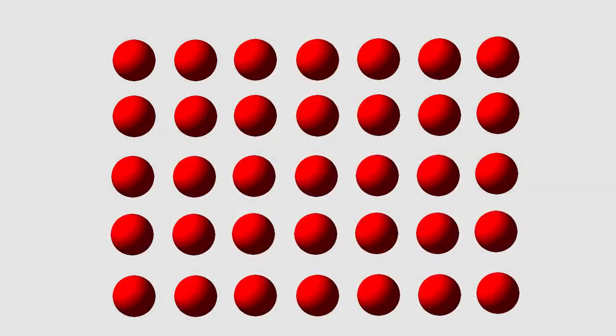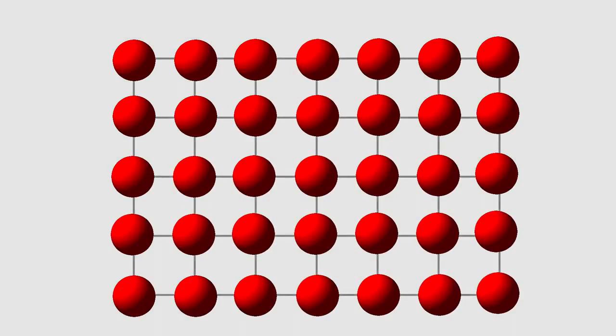Here's a simplified two-dimensional version of the atomic structure of nitinol, but one that captures the essence of why it has a temperature-dependent memory. The crystallites in the small grains have a nice, tidy, highly symmetric arrangement. The atoms sit on the corners of squares. At temperatures above 500 degrees Celsius or so, the nitinol can be shaped into whatever form is useful. For example, the spring I showed you earlier.